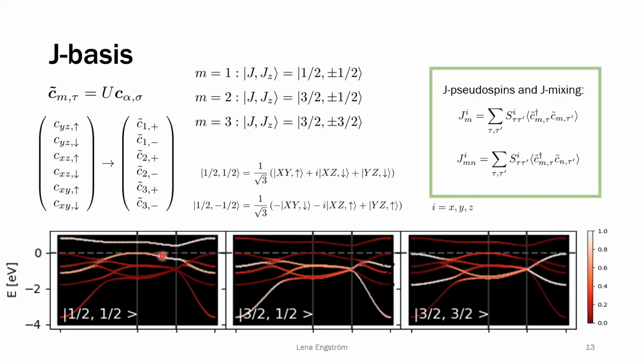the 1/2, 1/2 basis pretty much solely describes the top bands here, which for the effective model that we considered before, we said that we could have one state that only described the top bands, and it seems to be this state mainly. But we do have some extra states, especially from the 3/2, 3/2 here, on one point of the Brillouin zone, where it comes close to the Fermi surface.